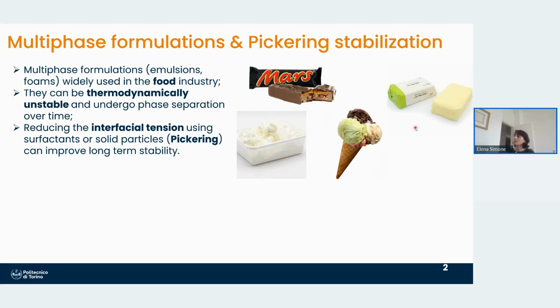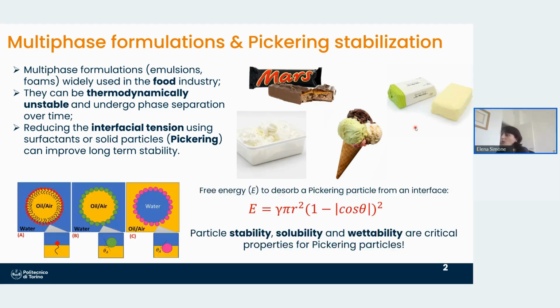Now, the problem with emulsions or foams is that they are made of two immiscible phases, so they are thermodynamically unstable and they can separate over time. So what we can do is we can try and stabilize them either using surfactants, which is the usual strategy, or we can use solid particles, and this is called Pickering effect. Now, compared to surfactants, solid particles are very strongly adsorbed at interfaces, so they provide quite stable formulations.